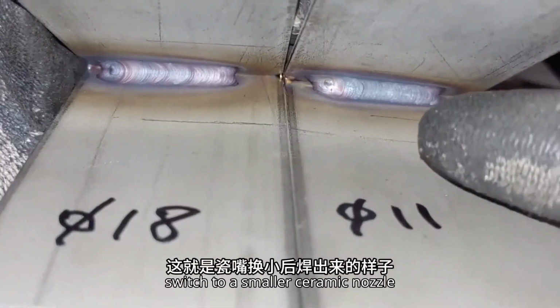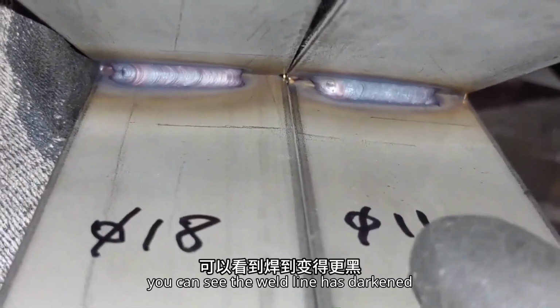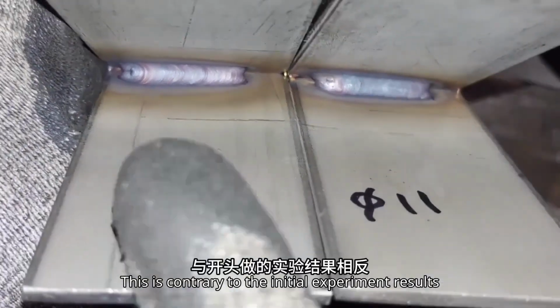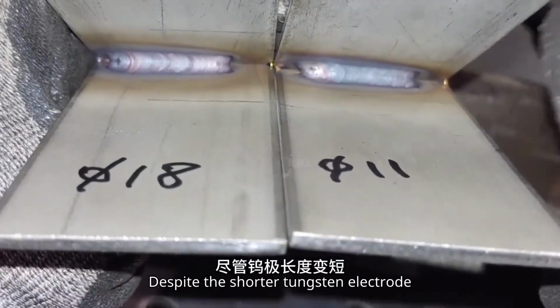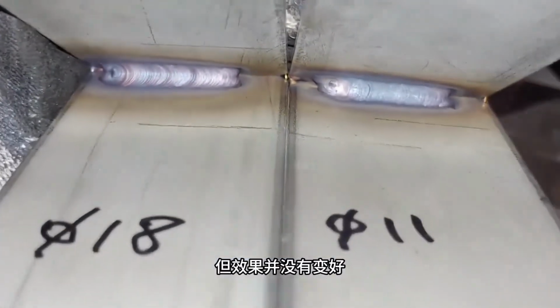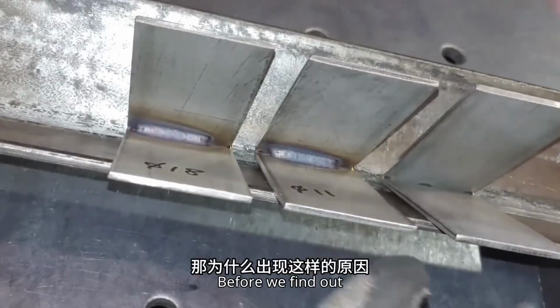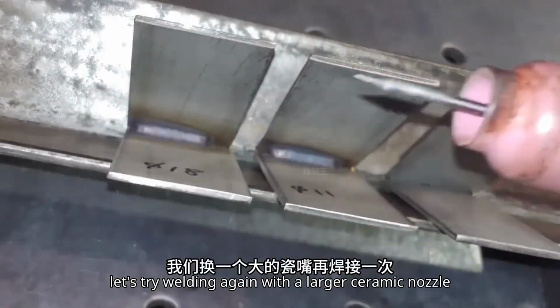This is how it looks when we switch to a smaller ceramic nozzle. You can see the weld line has darkened. This is contrary to the initial experiment results. Despite the shorter tungsten electrode, the result hasn't improved. So why does this happen? Before we find out, let's try welding again with a larger ceramic nozzle.